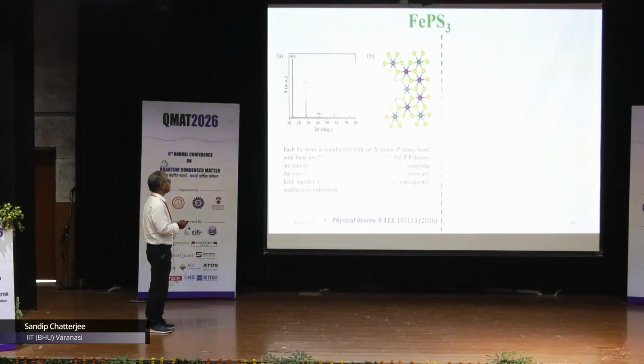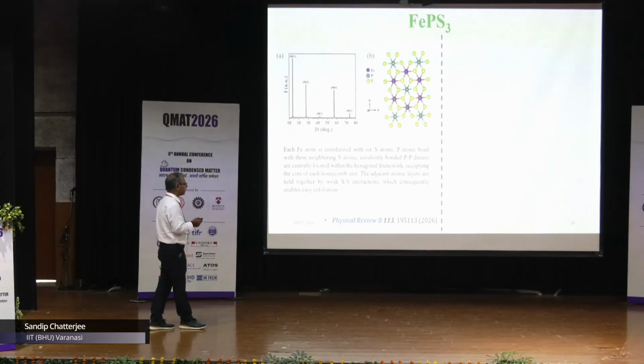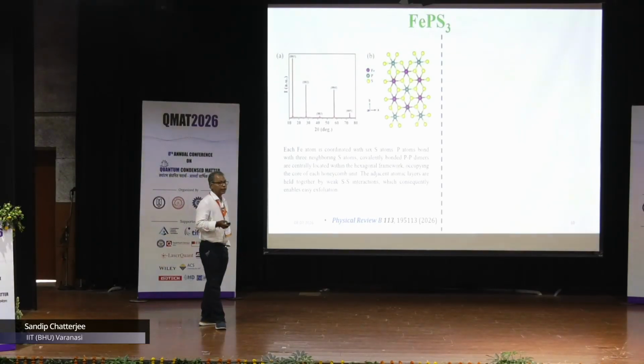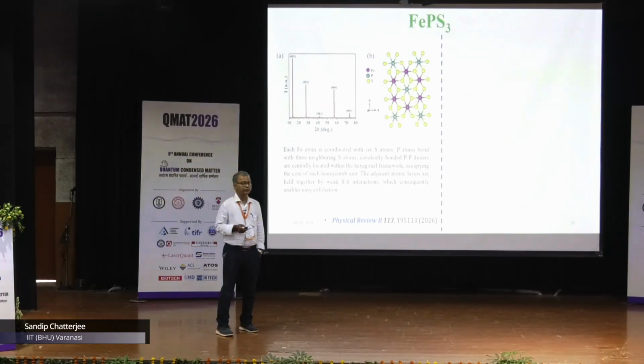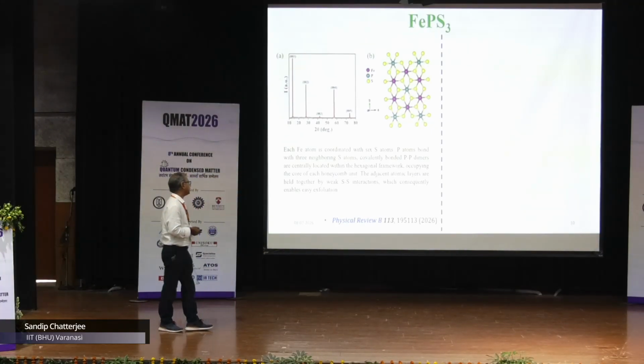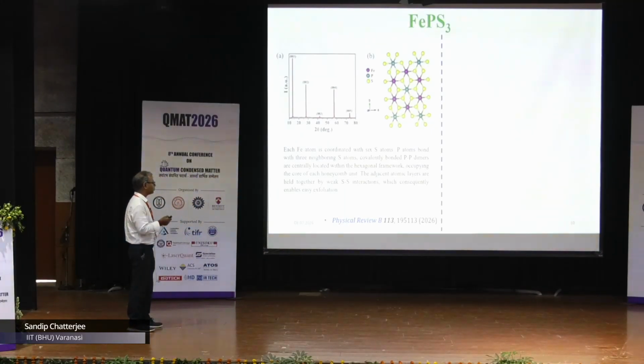We prepared the FePS3 material by the chemical vapor transport (CVT) technique and obtained flakes, and X-ray diffraction clearly shows a single crystal.